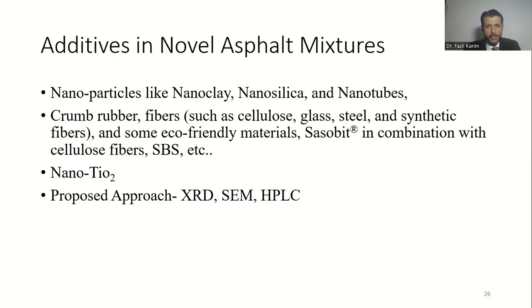And for the micro level studies, we use X-ray spectroscopy, scanning electron microscope, and also high performance liquid chromatography is sometimes very essential. As you know, aged asphalt, recycled asphalt, is lacking saturates, aromatics, resins and asphaltenes, and therefore I personally use various types of rejuvenators in the aged binder so that we can bring life to the aged binder. These rejuvenators enhance the percentage of SARA components, saturates, aromatics, resins and asphaltenes, in bitumen. And here again, I use TiO2 for the rejuvenator, which produces a coat around the rejuvenator, and then wherever it goes in the bitumen, that can be easily detected.